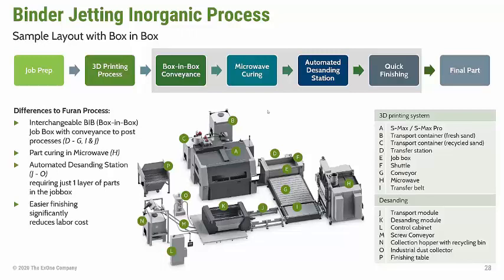After curing, the box gets transferred to the automated desanding station, where unpacking of the parts can start. The sand will automatically drop out of the box through openings at the bottom of the box, and this will allow to desand the box about 95% faster than what it would take for normal manual unpacking. However, to be able to make use of this time saving, it is most practical to print just one layer of parts in a box to avoid that parts would drop on top of each other.